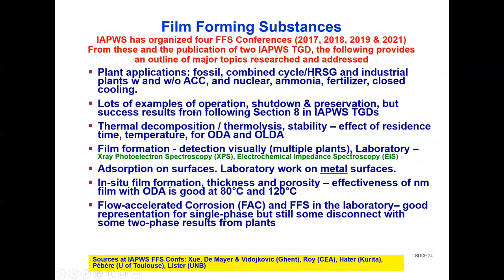There's lots of examples that we've seen on operation, what happens during operation when we have these compounds, and shutdown and preservation. Some of the science has been addressed. Thermal decomposition is the main one, and this has been done essentially for ODA, but also a little bit for OLDA. Film formation has been looked at. Detection visually, you can do that in the laboratory by looking for the hydrophobicity, and in the laboratory with XPS and EIS. There's work on absorption on surfaces, and there's also work on understanding the actual film formation itself. Some very nice work that was just done in the last year looked at how thick these films are, typically 10 nanometers, and the work has essentially been done with ODA.